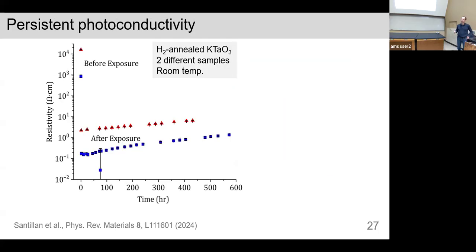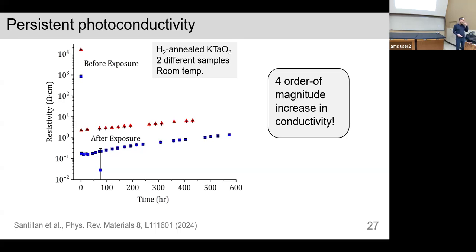So here's the evidence for persistent photoconductivity. Using Hall effect measurements in our lab, we measured the resistivity, Macarena measured, before exposure to light and after exposure to light. And so there is some variability from sample to sample. But you notice that before exposure and after exposure, there's a 1, 2, 3, 4 order of magnitude drop in the resistivity. This is at room temperature, and it lasts for many hours, in fact, many weeks. So there is some recovery as it drifts up like that, but it's pretty slow. You would have to wait. So it's a 4 order of magnitude increase in conductivity, and to fully recover, we extrapolate that you'd have to wait a couple of years for it to get back to its original resistivity at room temperature. So really persistent.